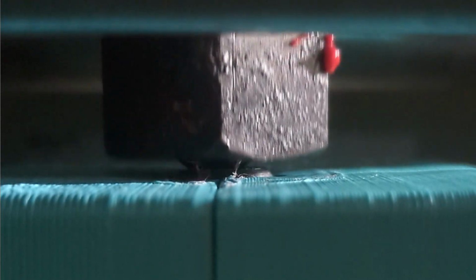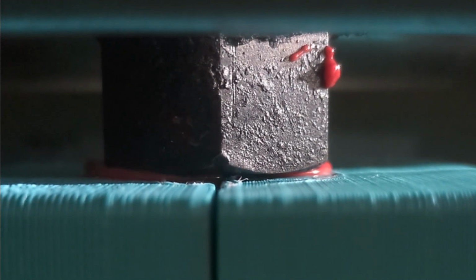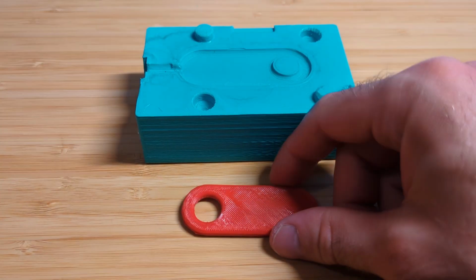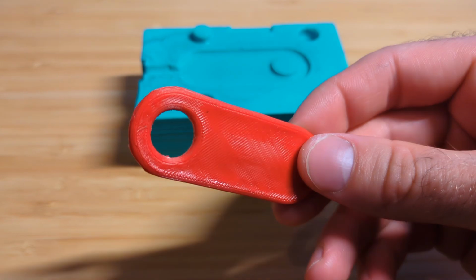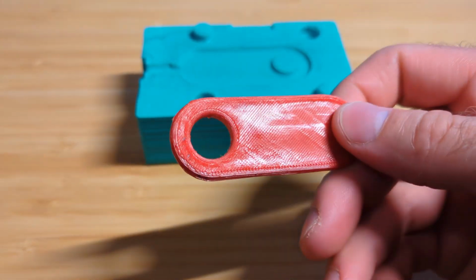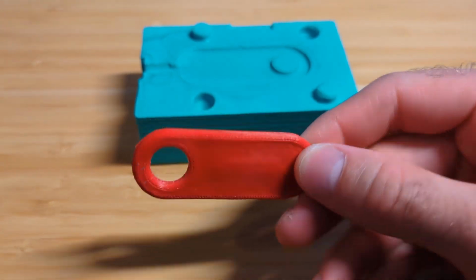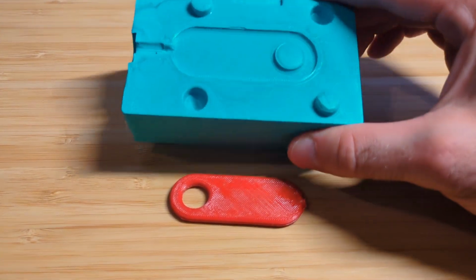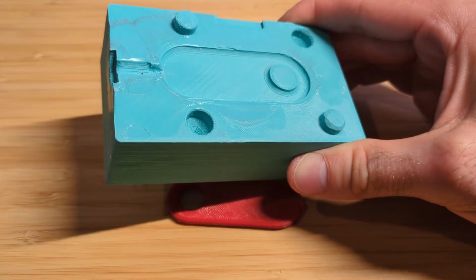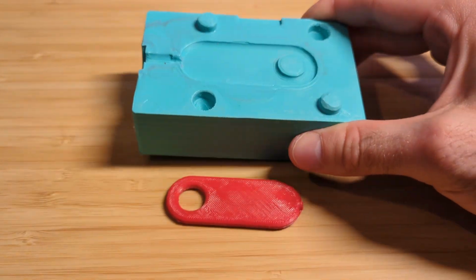So the only thing we had left to do is to start making some injection molding tooling. We used their teal HT-PLA, the Power Tool red HT-PLA-GF, and I'll run you through some of the process and the results that we ended up with. Here's the part getting injected. The metal ring is actually the contact surface between the nozzle and the tool. We ended up making 13 HDPE parts, and I'm happy with how it turned out. Initially, I wasn't certain if we were even going to get the tool halves apart after the first shot. And because of that, I did over-inject in the beginning to give myself a better chance of getting them to pull apart, and you can see those witness lines.